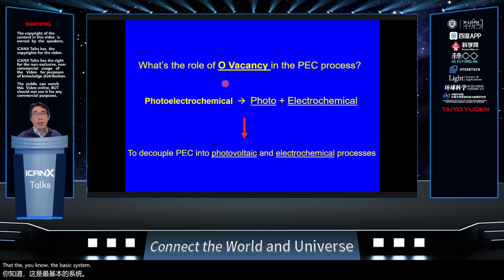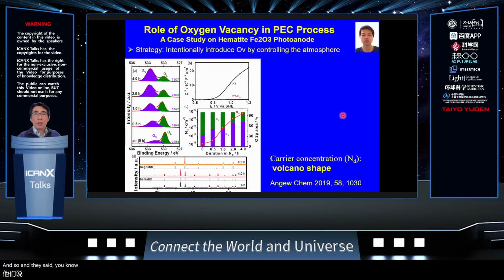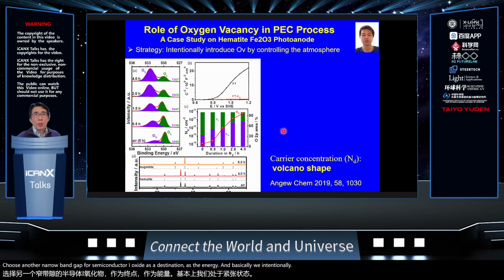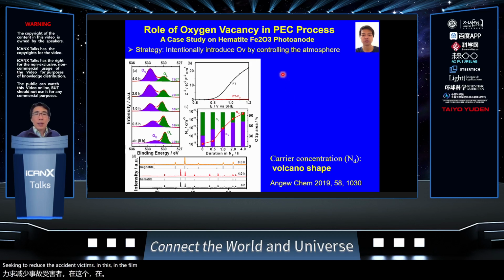If you look at this one word, photoelectrochemical, we can split it into two, cutting in the middle: one is the photovoltaic effect, the other is the surface chemical, electrochemical reaction. This was conducted by Lianzhou Wang, who chose another narrow bandgap semiconductor, iron oxide, as the photoanode. We intentionally introduced oxygen vacancies in the film by controlling the atmosphere when we do the calcination.